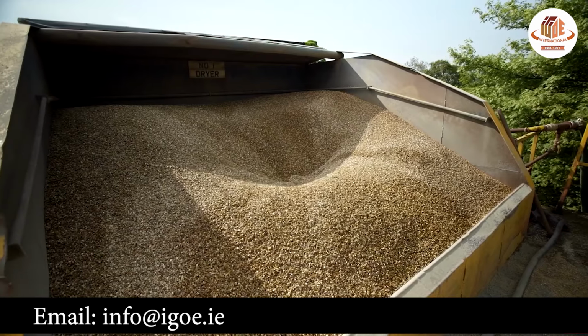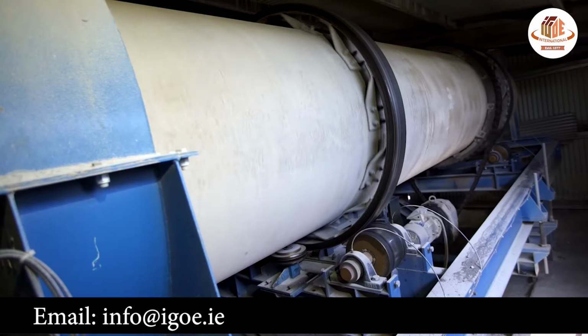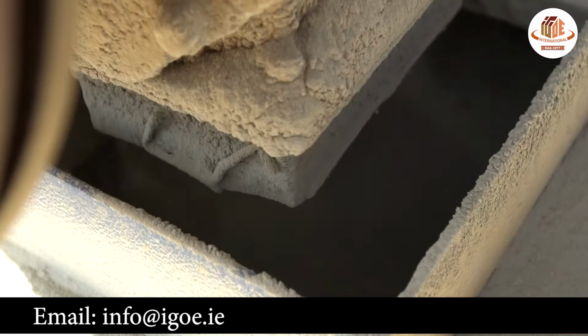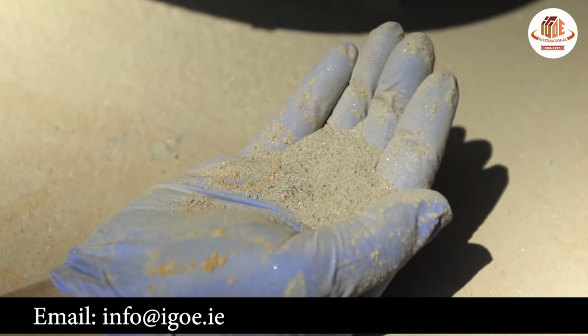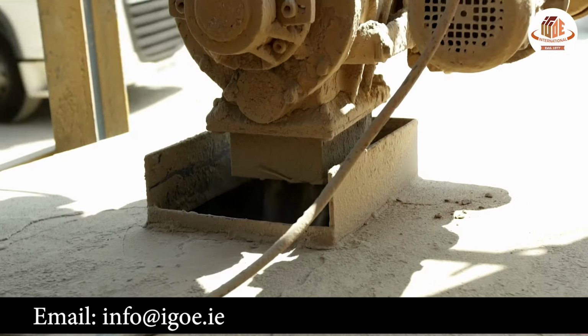The aggregate must be dry. Do not use aggregates that appear to be damp in bags, as the resin may react with the moisture and lead to clouding and patching. Dust can soak up resin and create a cloudy finish. It is impossible to remove all dust from aggregates.